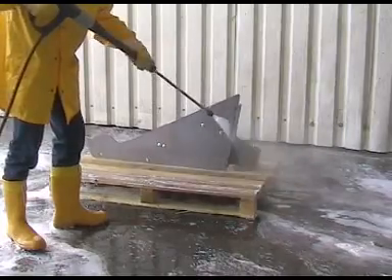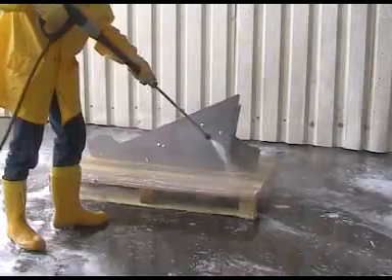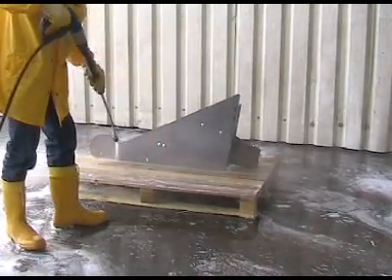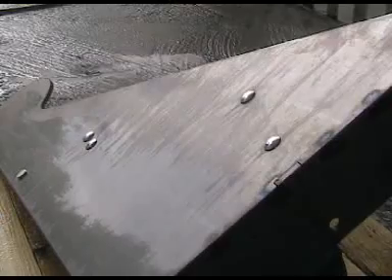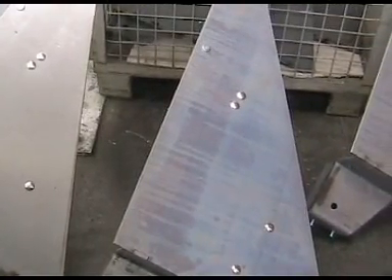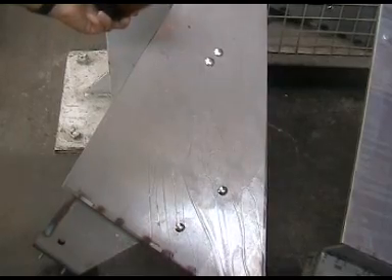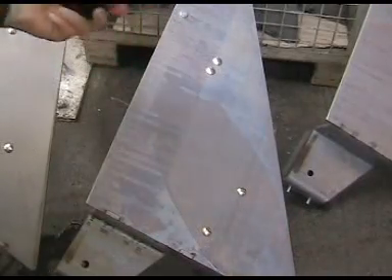The workpiece is then rinsed with hot water, preferably low in lime or demineralized. Compared to an untreated workpiece, the phosphated workpiece has a bluish-grey coating. The very good wetting property, tested here with distilled water, confirms the success of phosphating.